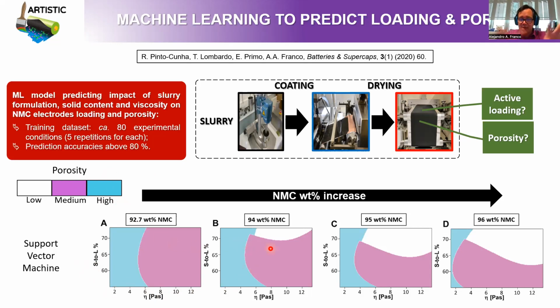And here you see that this output is telling you that in order, for example, to make electrodes with low porosity, which in this case means electrodes with more or less 30 to 35% of porosity, you need to choose the appropriate content of NMC, the appropriate formulation. And also you need to choose the appropriate viscosity for your slurry and the appropriate solid content, okay? Because if you choose, for this case, a viscosity which is too low and a solid content, whatever value you want between 60 and 70, then it will be impossible for you to make electrodes with low porosity. If you want an electrode with low porosity, you need to increase the viscosity value and mostly use high solid contents, right? So this is the kind of outcome that this kind of machine learning modeling can give you, right? And we believe that this is very useful for experimentalists because this is a kind of phase diagram, right? It can be very easily understood by, for example, the technician who is making battery electrodes in the pilot line, right?